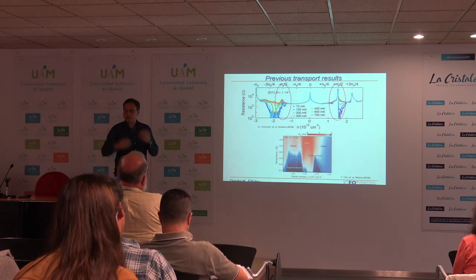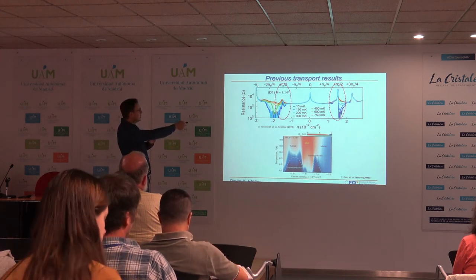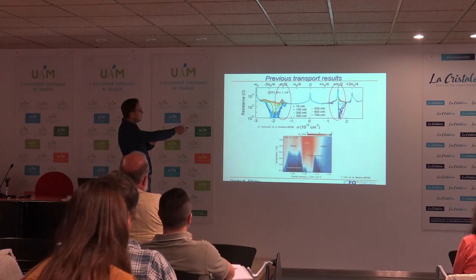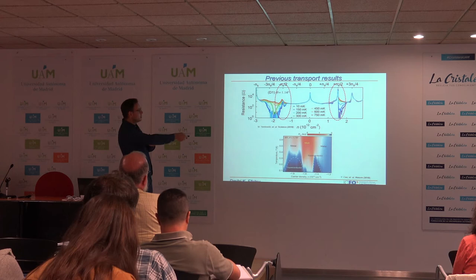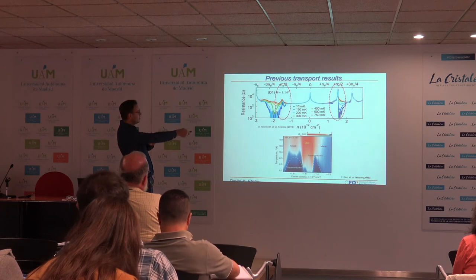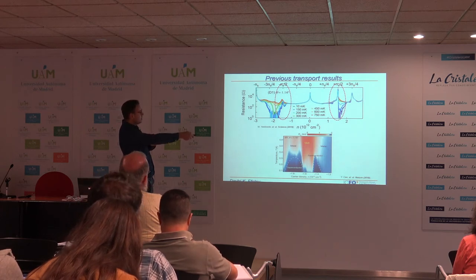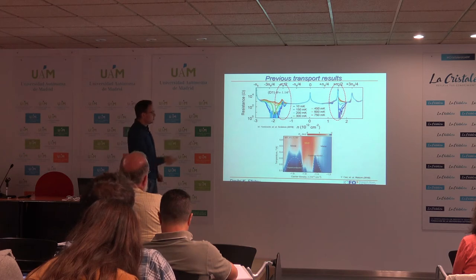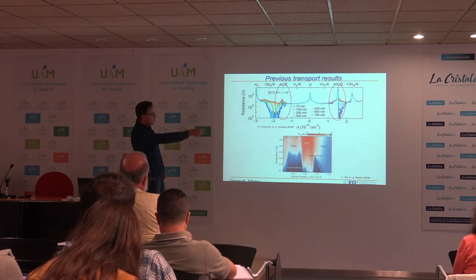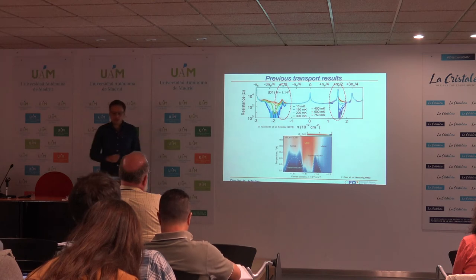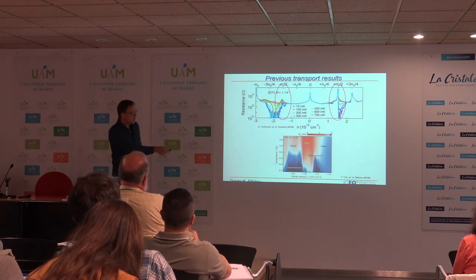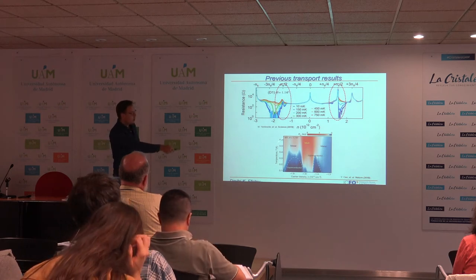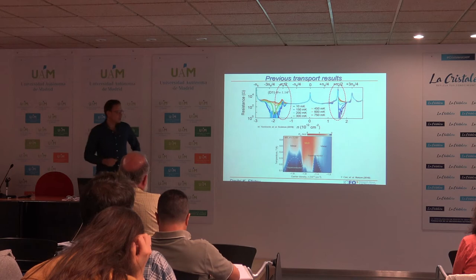If we start at the band edges where we have these band insulating states, we get megaohm resistances, but then if we start filling up the gap, we first get these superconducting states where the resistance basically drops to zero. Then we get, exactly at half filling, at minus ns over 2, insulating states, and then we also get insulating states at plus n equals 2. And these locations at minus 2 electrons per unit cell and plus 2 electrons per unit cell are exactly the locations where Pablo first observed these Mott-like insulating states, which are then flanked by the superconducting states. Okay, so we repeated the same measurements now.